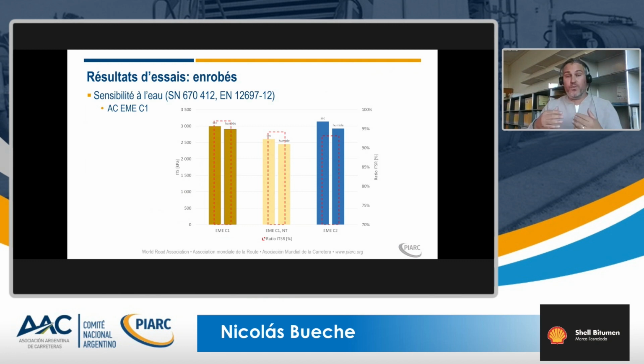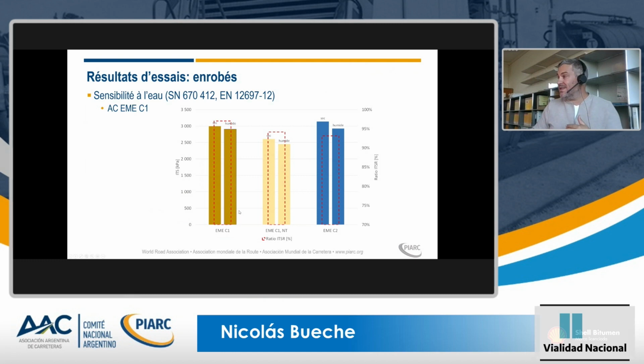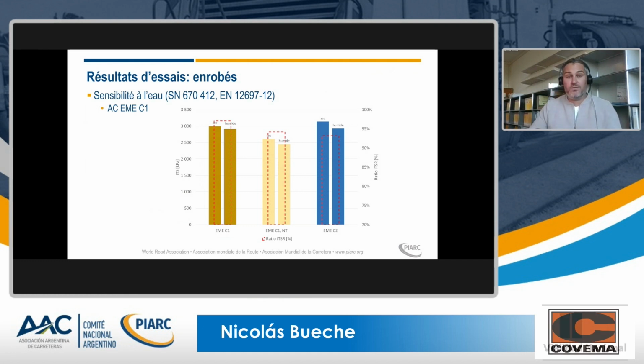And basically, we have to reach a target value of 70%. We can see for every asphalt mixture, so hot and warm, we get ITSR ratios which are, let's say, between 91 and 96%, which is quite good. Based on this, we can say we didn't have any specific issue related to water sensitivity of the hot or warm mixed asphalt.